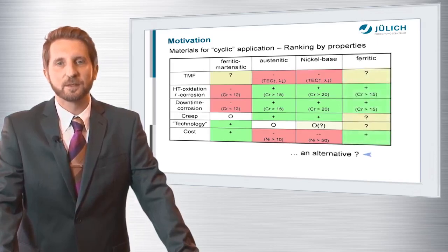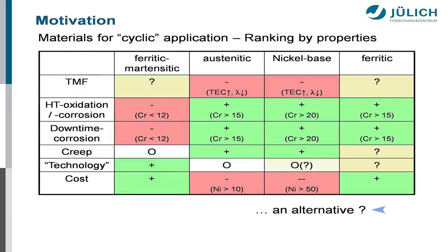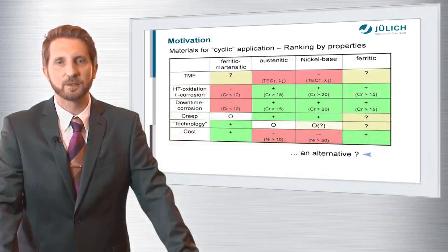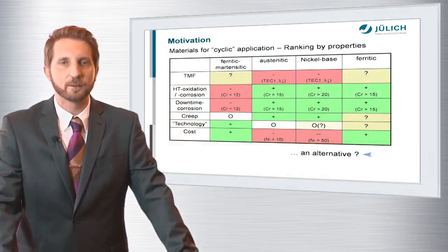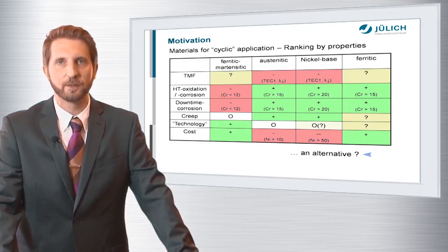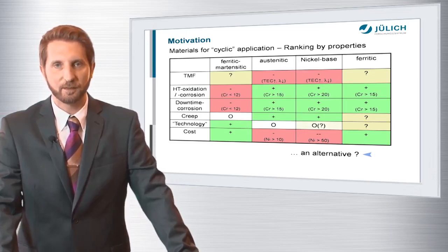So the question is, there is a fourth material class, the ferritic steels. These steels traditionally are not regarded for structural application in high-temperature power generation. And that is for the reason that this material class is typically considered to be not creep strong enough. But what is for sure is that corrosion issues should not be a problem because the ferritic stainless steels mostly do feature chromium contents higher than 15%, which would be enough. And cost should be another advantage because they will not be much more expensive than the ferritic 9 to 12